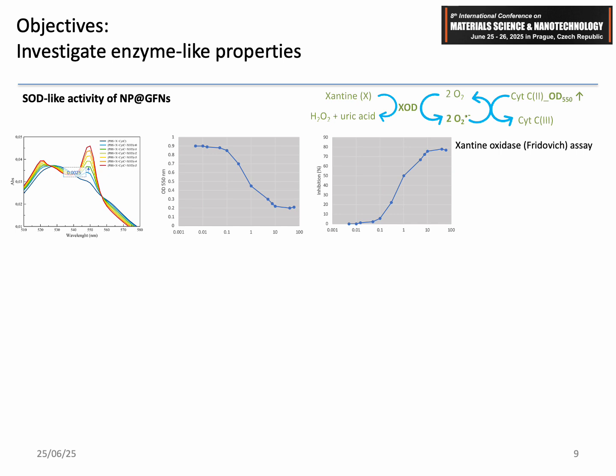Then let's move to the functional characterization of our palladium GO hybrids, focusing on their SOD-like activity. We use the Fridovich method, which is a colorimetric assay that employs a xanthine oxidase system to generate superoxide anions. These radicals reduce cytochrome C3 to cytochrome C2, which absorbs light at 550 nanometers. The SOD and SOD-like nanozymes slow the reaction by scavenging superoxide radicals, causing a decrease in the absorbance over